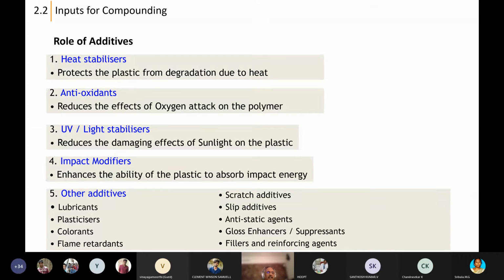When PVC was initially discovered, you could have noticed it was in the 19th century, but the commercial use started only in the 20th century. The reason is people were not able to process rigid PVC. It would immediately degrade. A catalytic reaction will happen, so quickly it will degrade and it will char. So people were not able to use it. Then the addition of plasticizers, lubricants and so on made it possible to make use of PVC. So plasticizer is very, very critical for PVC.